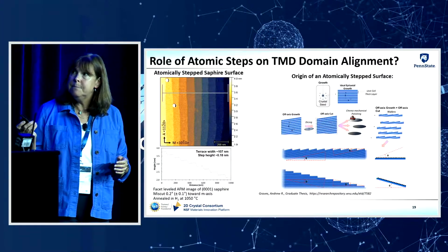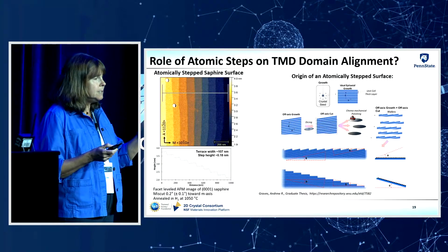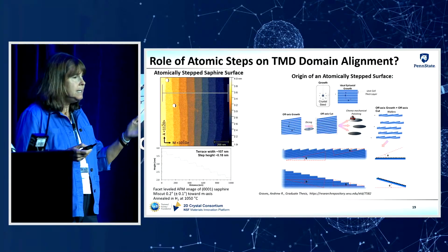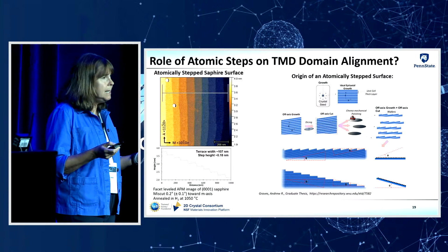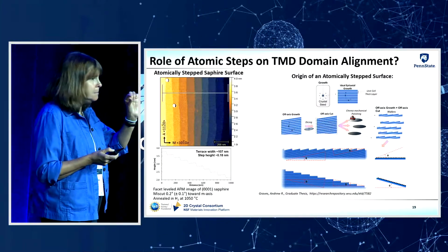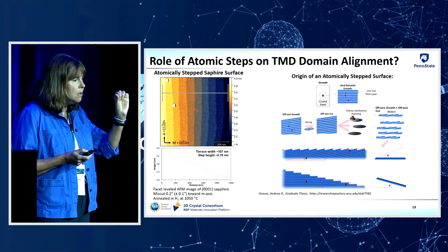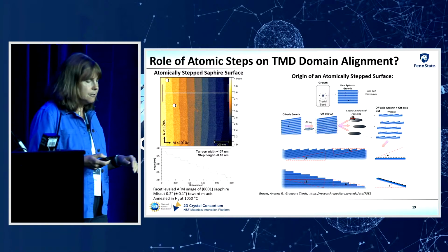So this is an AFM image of our sapphire surface with steps and terraces. You can see that the terraces are about 100 nanometers in size. The steps are maybe about 0.2 nanometers tall. So very small steps across the surface.